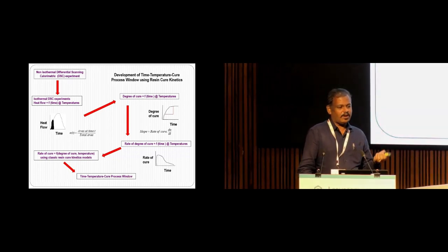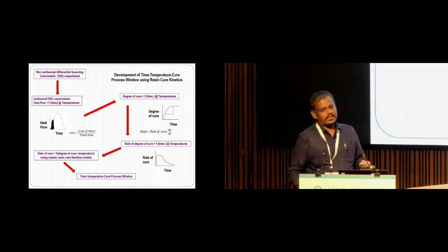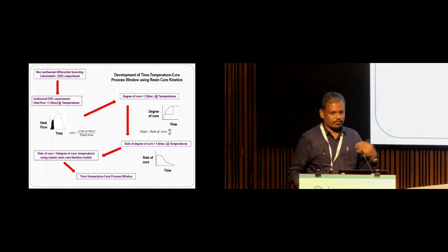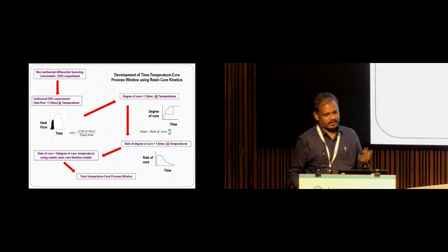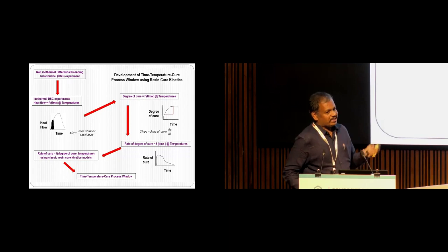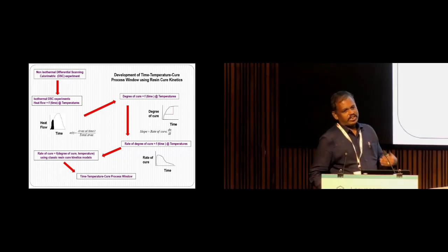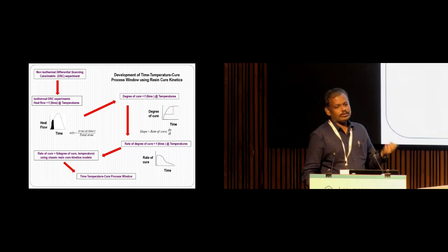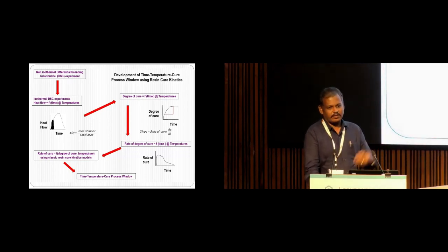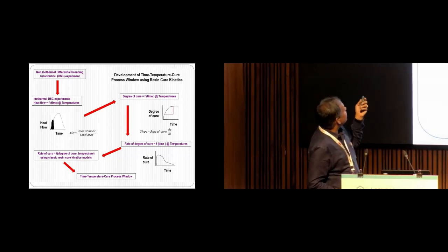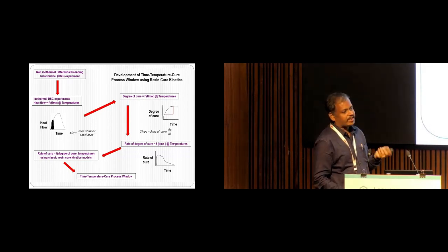At first, you have to perform the thermal characterization, the dynamic thermal characterization through DSC. That means a 10 degree per minute ramp. You have to do it from room temperature, or storage temperature, to maybe 400 degrees centigrade, the thermal degradation temperature of the resin. Since the resin curing is exothermic in nature, the heat evolution behavior is recorded as a function of time with respect to the rise in ramp temperature. So at first you will get heat flow as a function of time at different temperatures.